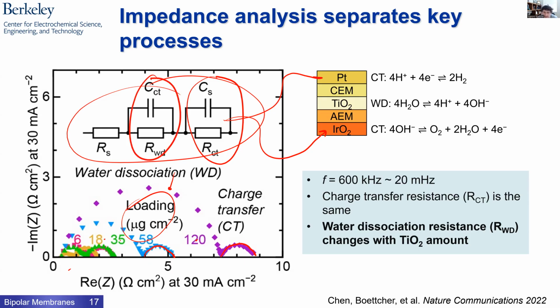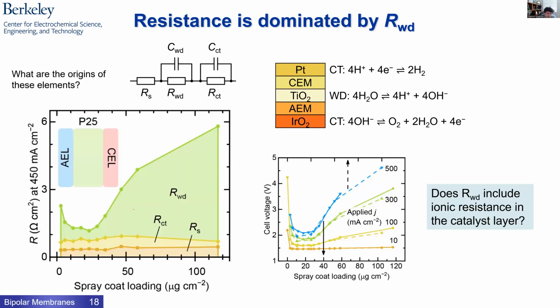And this one is associated with the process that's happening in the junction. That's why it's so sensitive to how much catalyst you have. Okay, so this is going to allow us to isolate the different relative impedances as a function of thickness for this catalyst. What you see here is pretty interesting. So the charge transfer resistance, that's the electrode. It doesn't really change, okay? There's some noise here, but this is independent of what you put in the middle.